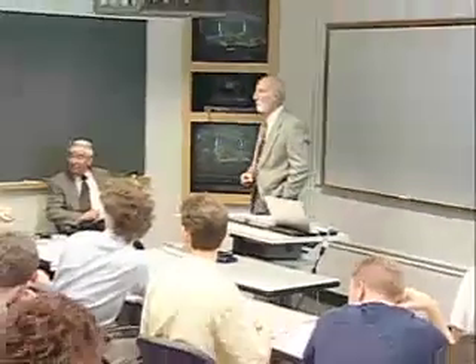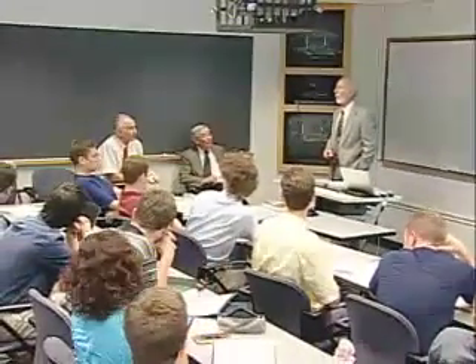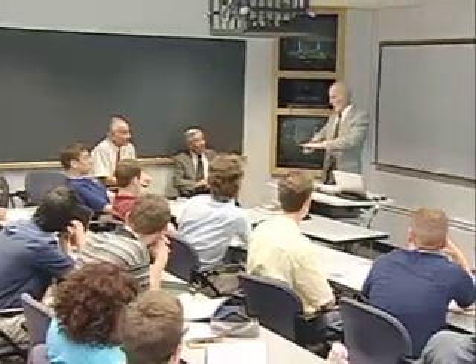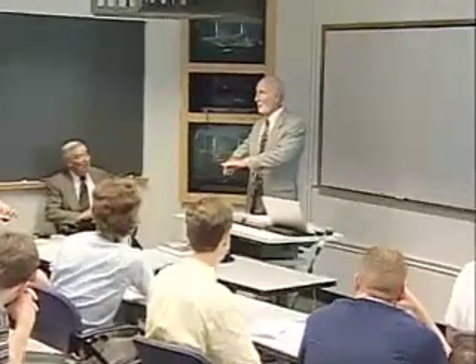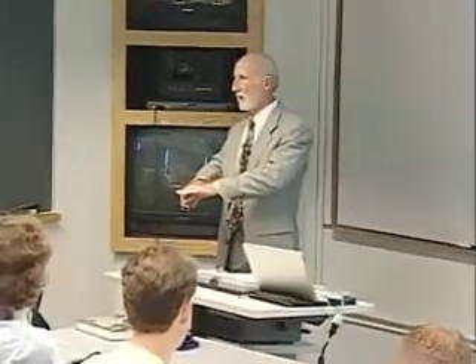Yes? There are gaps between the tiles. When you re-enter, do the tiles expand so that there are no gaps? No. What we do is we make sure that the gap can just close, but not close such that you're loading one tile relative to the other. So that set the gap. And if during manufacturing, which is not that precise, the gap was too large, we just stuck a gap filler in. It's a different kind of gap filler than the one on the last vehicle: just a piece of Nomex or SIP material, strain isolation pad, coated with rubber or RTV, and we stuck it in between the tiles just to reduce the flow if the gap was too large.